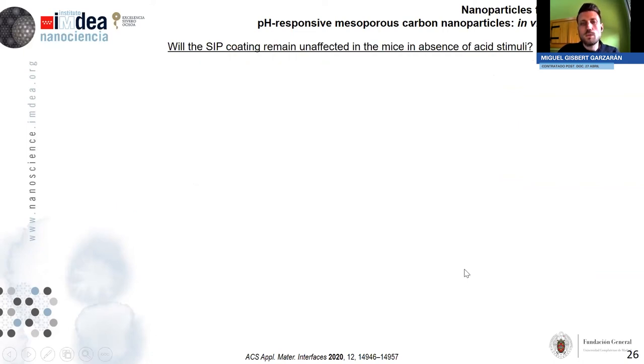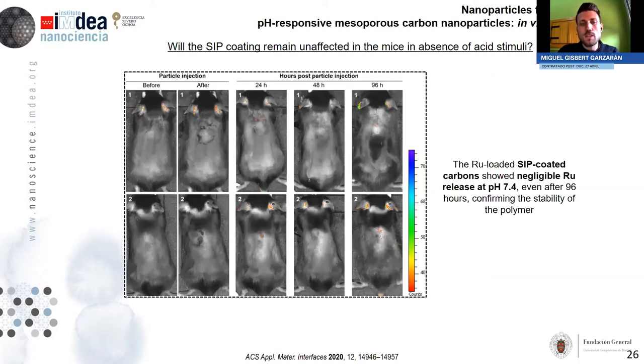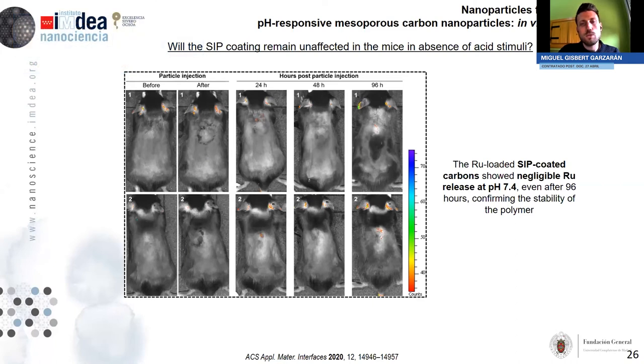So after that, we wanted to answer this question: will the SIP coating remain unaffected in the mice in the absence of acid stimuli? For that, we loaded the nanoparticles with a ruthenium dye. Then we administered the nanoparticles in a pocket under the skin of the animals, and we imaged them for up to 96 hours. As you can observe, the fluorescence intensity in all cases was always low, meaning that the SIP coating remained effective in a more complex in vivo scenario, and that the coating was able to keep the ruthenium dye within the pores.